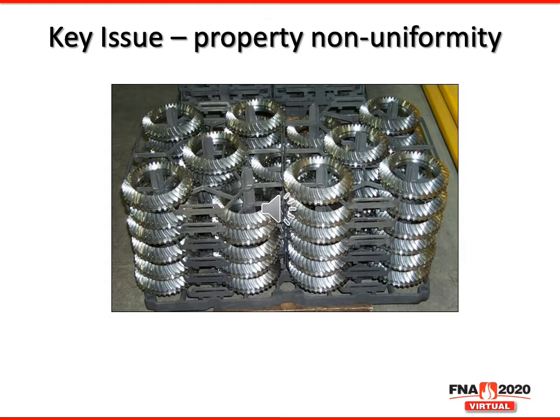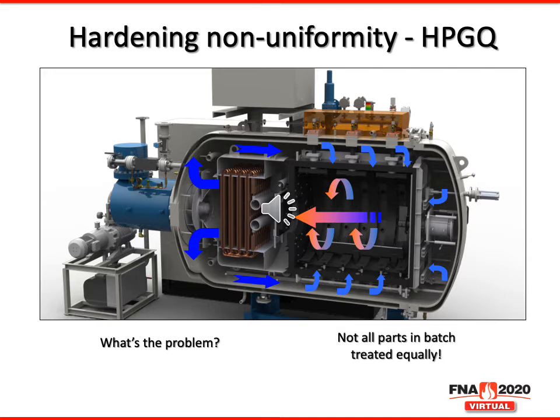What does this do? Well, it depends on the furnace type. In the case of a high pressure gas quenching furnace, the flow goes completely around the outside of the batch in the furnace. So as you'll see here, indicated by the blue arrows, the flow of gas is completely surrounding and impinging on the outside of the batch. Then it goes through the rear of the working or hot zone of the furnace into a heat exchanger, a blower, and then back around the outside of the hot zone. What does this do? Well, it allows for direct impingement of the gases on the outside of the load.